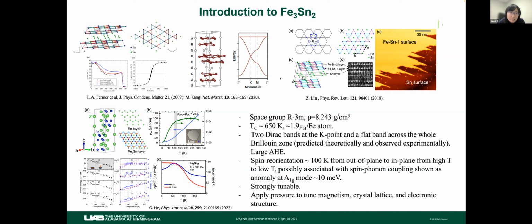The interesting thing about this system, because of the unique band structure, is that it shows a very large anomalous Hall effect, and it also orders at very high temperature, probably one of the metal Kagome materials with the highest magnetic ordering temperature. When you cool further down, there is a spin reorientation. In another paper, they reported a spin reorientation transition from out of plane to in plane when you cool down from high temperature to low temperature. Some studies show that it's possibly associated with a spin-phonon coupling shown at the A1g mode around 10 millielectron volts. That was done previously from a Raman experiment at low temperature.